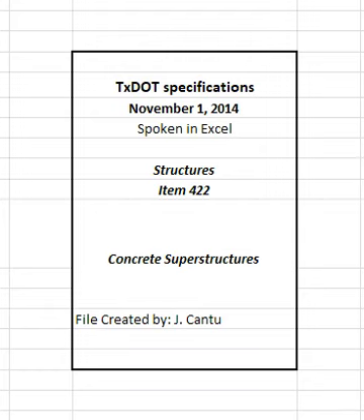Thoroughly consolidate concrete along construction joints by operating the vibrator along and close to but not against the joint surface. Continue the vibration until the concrete surrounding reinforcements and fixtures is completely consolidated. Hand spade or rod the concrete if necessary to ensure flushing of mortar to the surface of all forms. Concentrate vibration efforts along the beam lines when precast concrete panels are used for deck construction.